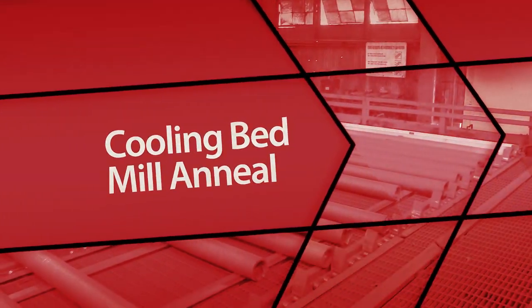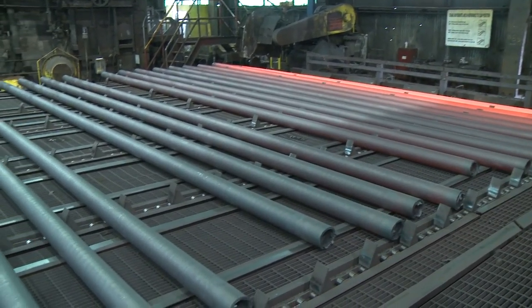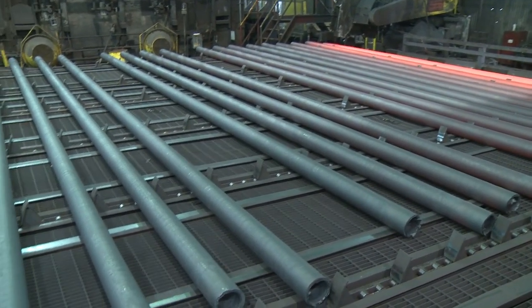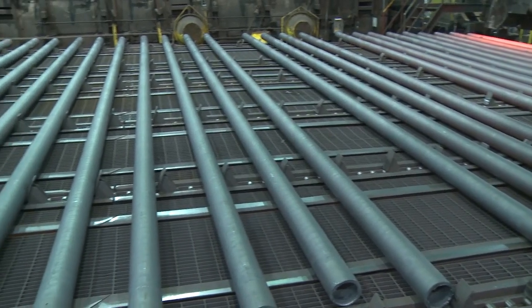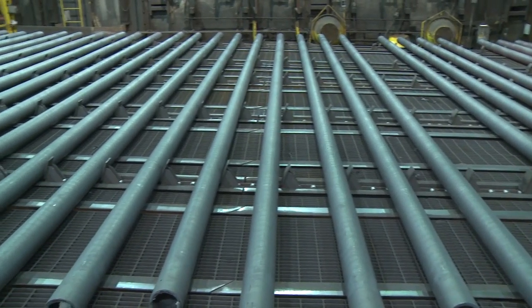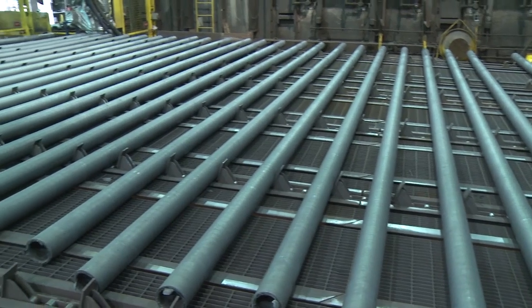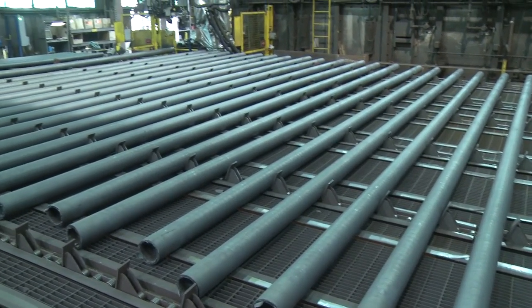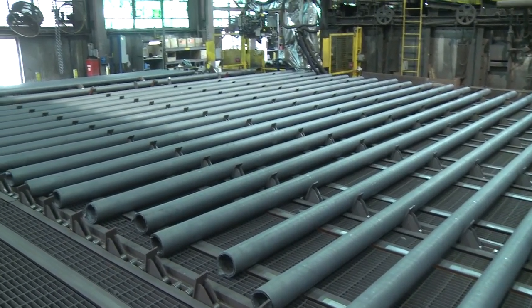The tubes then cool using a cooling bed or mill anneal furnace. The cooling bed rotates the hot-rolled tubes at a consistent pace to evenly cool the tube and maximize straightness. We can also use the mill anneal as a slow cool process to obtain desired microstructures for the tube.